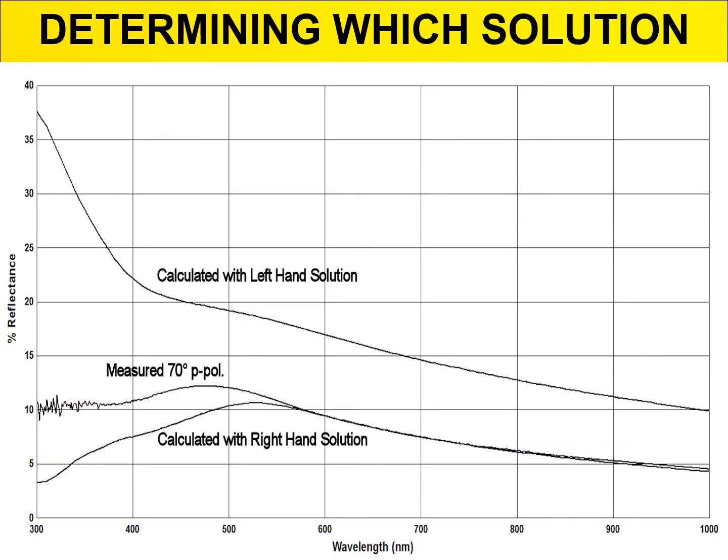Well, if I take a 4th spectral curve at an angle, like 45 degrees or 70 degrees or something like that, in P polarization is the best, then I'll find which one of these seems to agree. So here the agreement at the right-hand side of this curve is virtually perfect. It starts to depart at the left-hand side, and that's probably some various problem, but it's definitely not the top curve that is of that nature, it's the bottom one. So we have a good solution.